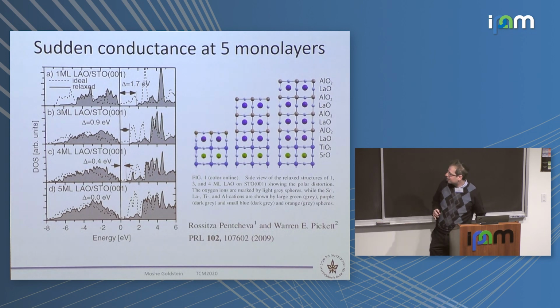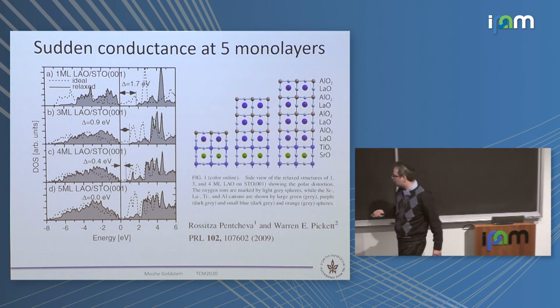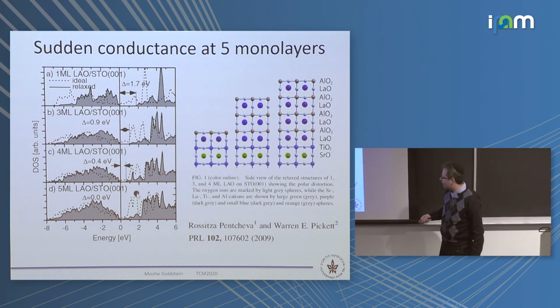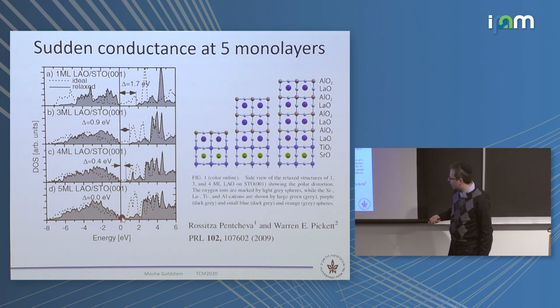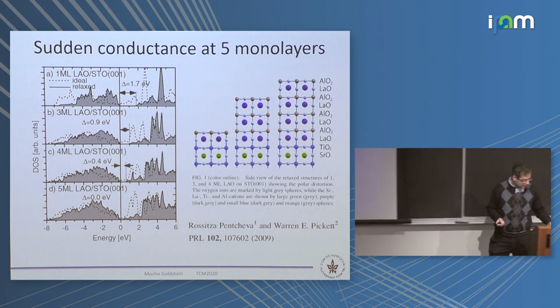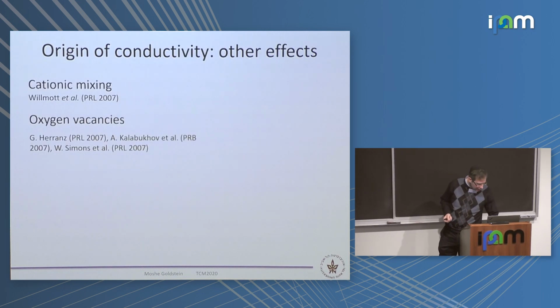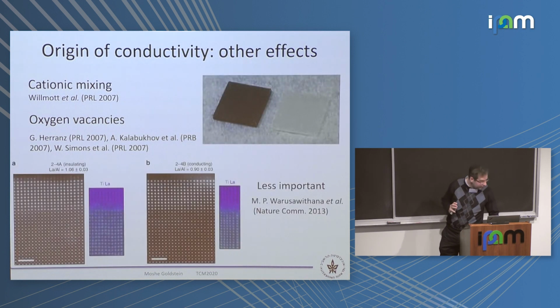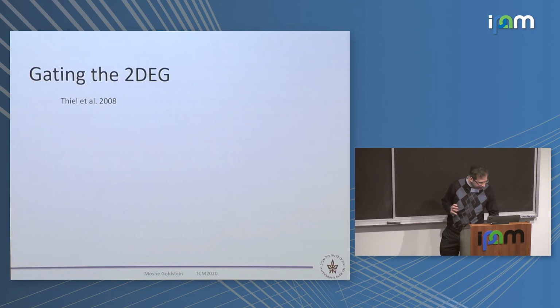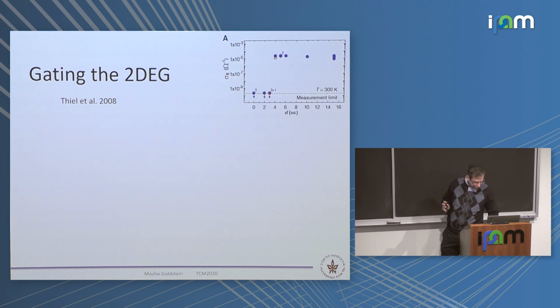And then you can do something more sophisticated ab initio, and this also shows you that when you have enough layers, 4 or 5 of LAO on top of STO, you close the gap and get conduction at your Fermi energy. Okay, there are other things that could contribute to that, but they are not important. Let me skip this. Okay, and then, I told you that this is interesting because, like semiconductor heterostructures,